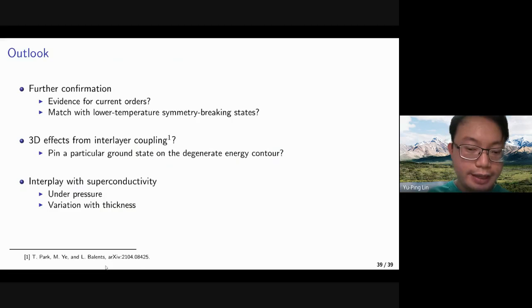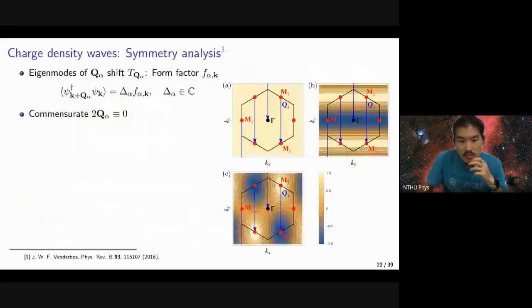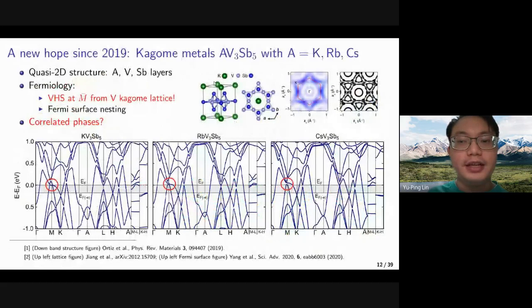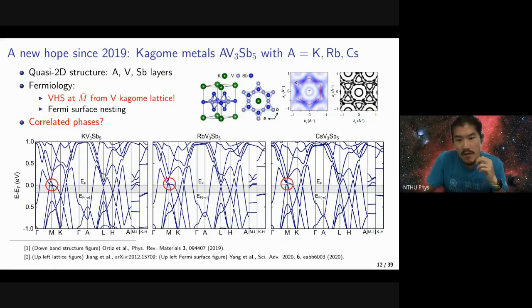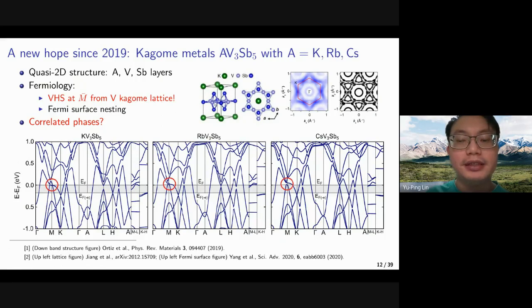Actually, this question has somehow been answered to a certain level by this work. So they propose that because the kagome metals have quasi-2D structure, if we look at the lattice structure here, the potassium layers are nearly decoupled from the vanadium and the antimony layers. This means that the vanadium plus antimony layer may also be nearly decoupled from the other layer. So the relevant charge density wave might be the charge density wave that develops in the 2D structure. And to address the 3D effect, it might be addressed by thinking about the secondary coupling between the charge density waves of different layers.